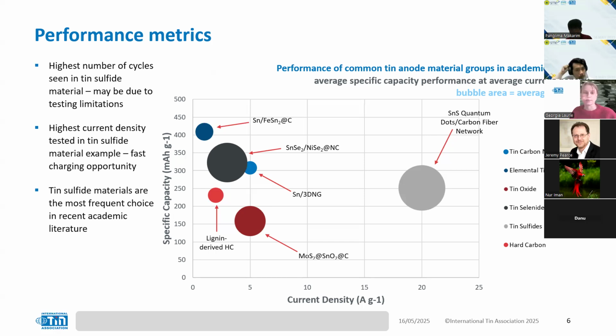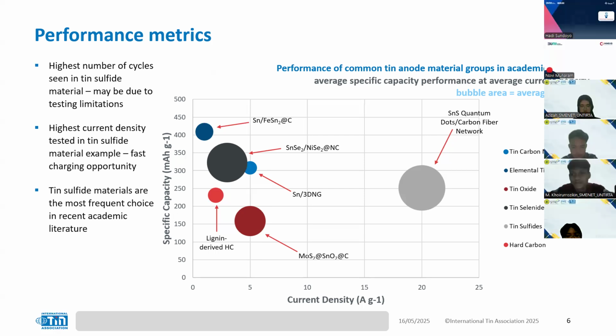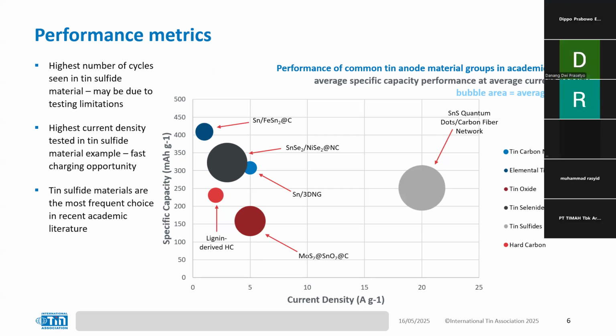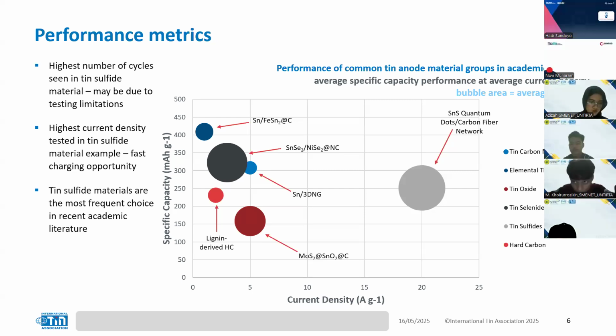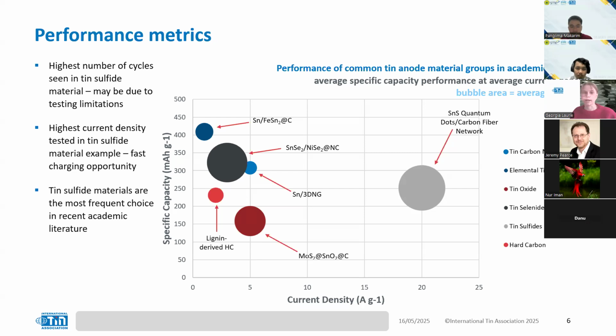So if we look at this specific example of tin sulfide quantum dots on a carbon fiber network, it's been tested at a very high current density of 20 amps per gram. So you can see that it's a lot further on the right-hand side on the graph because it's being tested at such a high current density. It also is a large bubble because it's been tested over a lot of cycles. So it's been tested for 10,000 cycles. And it's able to maintain a specific capacity of over 250 milliampere hours per gram.